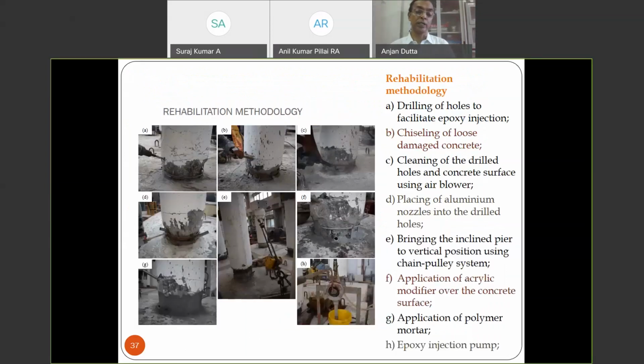Right. So the specimens which we have tested earlier using fiber reinforced polymer, hybrid fiber concrete, those damaged specimens we are now rehabilitating. We have done rehabilitation using the standard rehabilitation procedure. We have cleaned all those loose concrete. We have done some patching using micro concrete.